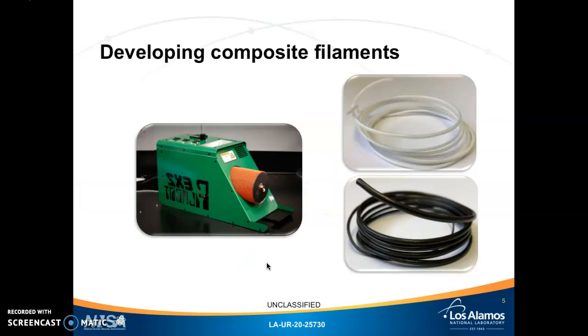The image on the left is of the extrusion instrument we use, where the composite materials are fed into the hopper, which is the opening on top, and a heated metal screw pushes the material through the nozzle to create the filaments. On the right, there are examples of filaments we created using this method. The top image is of an ABS PVDF 50 by 50 weight % filament, and the bottom is ABS bismuth 50 by 50 weight % filament. These are of constant diameter and smooth enough to be fed into a 3D printer.